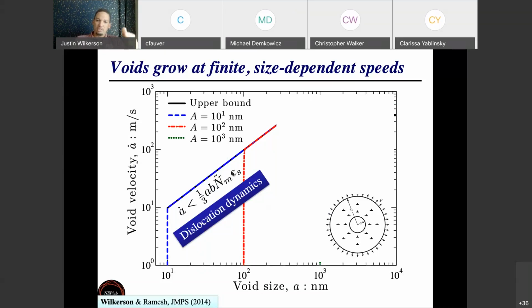And that has some similarities to the propagation of the twin boundary. Remember, for twin boundaries, they couldn't move any faster than the shear wave speed, and then there was a spacing of the twinning partial dislocations that came into play. So here it's the spacing of the mobile dislocations that comes into play, the shear wave speed, and then what's different about voids is as they grow,